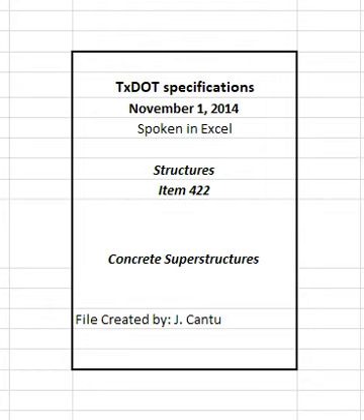Use tremies that are watertight to control the fall of concrete and of large enough diameter to allow the placement of the concrete but less than 14 inches in diameter. Use pumps with lines at least 5 inches inside diameter, ID, where grade 2 or smaller coarse aggregate is used, and at least 8 inches ID for grade 1 coarse aggregate.